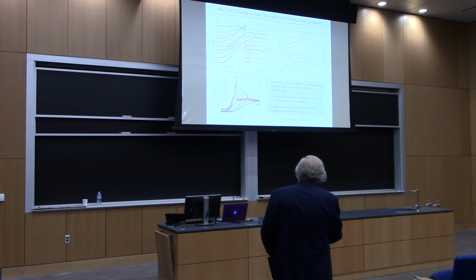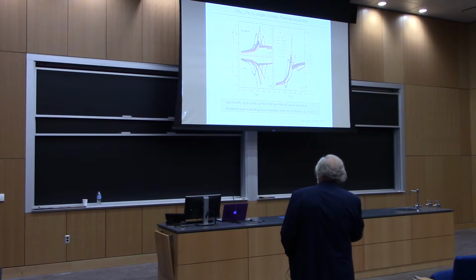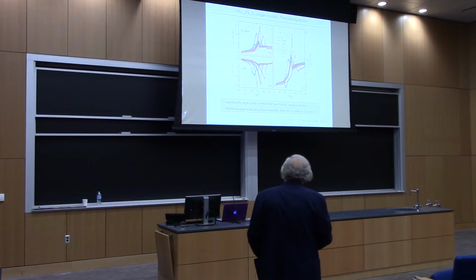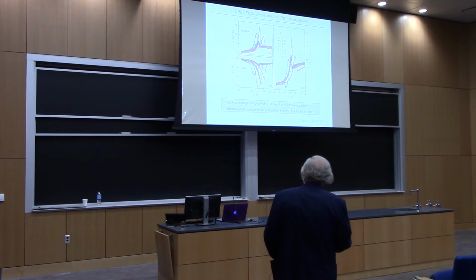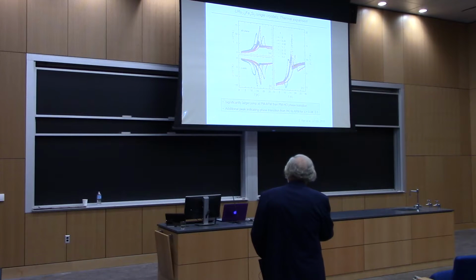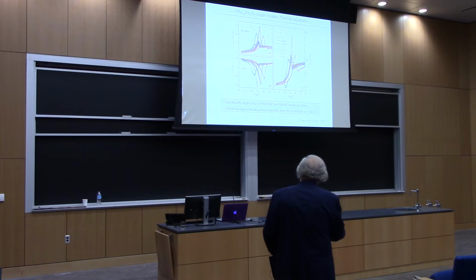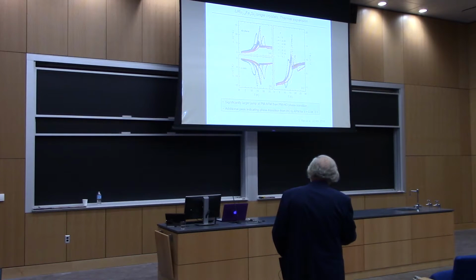And then these are the actual specific heat data. So you see very sharp transitions in the hidden order phase, and then they become broader and shift to higher temperatures in the antiferromagnetic phase. And this is more recent data on thermal expansion. So this is for the ab plane, this is along the z-axis, and then this is the volume thermal expansion that you can derive from these data.